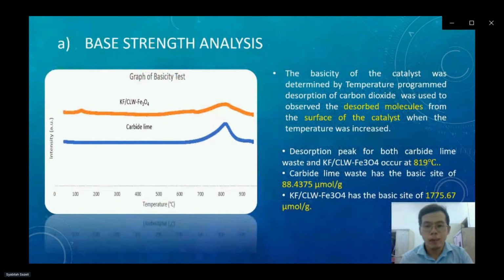Next, the basicity of the catalyst was determined by temperature programmed desorption of carbon dioxide to observe the desorbed molecules from the surface of the catalyst when the temperature increased. As you can see from the graph, the desorption peak for both carbide lime waste and the KF/CLW/Fe3O4 occurs at 819 degrees Celsius. Carbide lime waste has a basic site of 88.4375 micromole per gram, while KF/CLW/Fe3O4 has a basic site of 1775.67 micromole per gram. It means the basic sites of the KF/CLW/Fe3O4 and carbide lime are in good agreement with the Hammett indicator tested before.